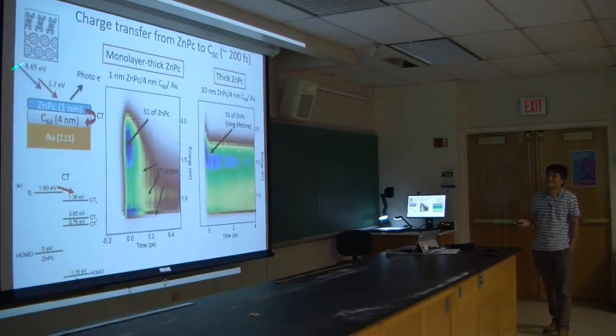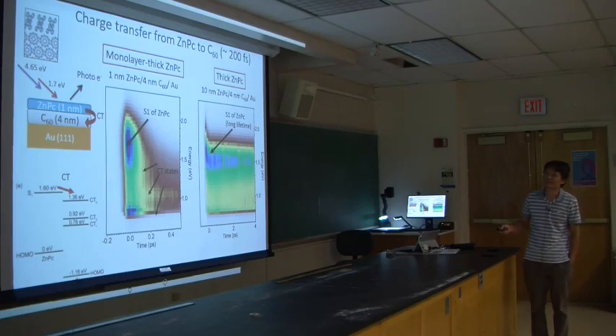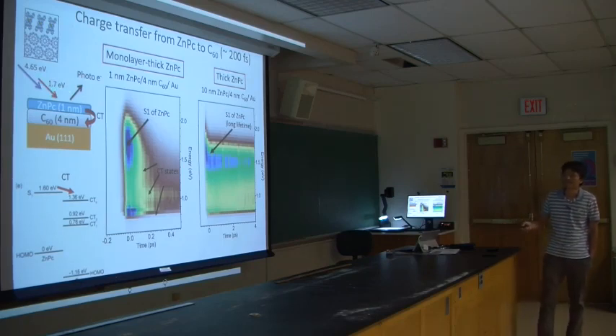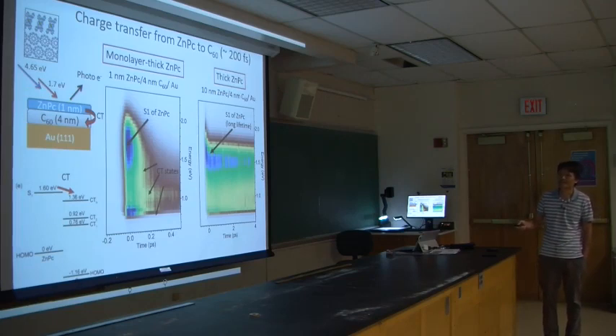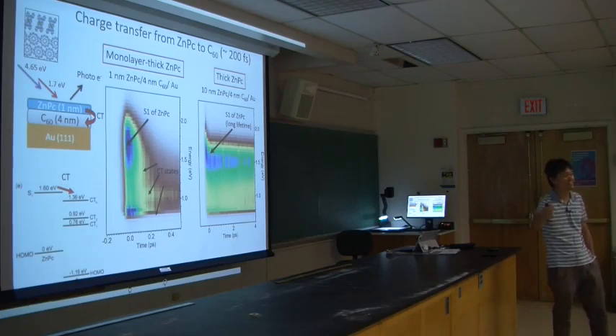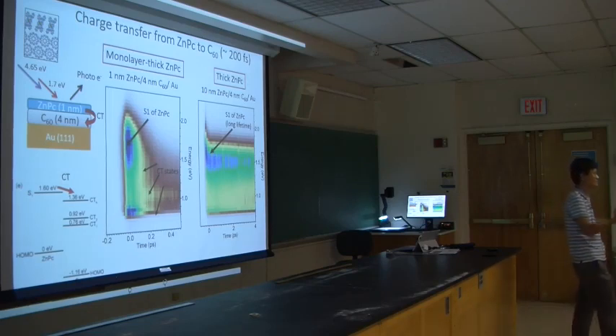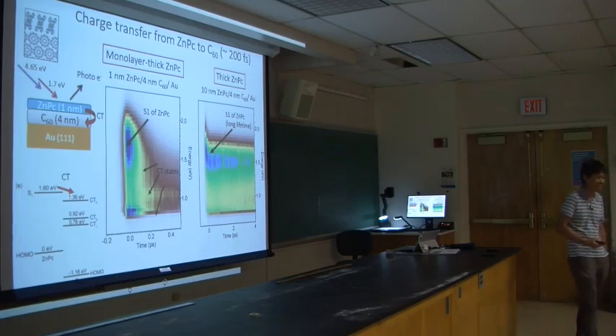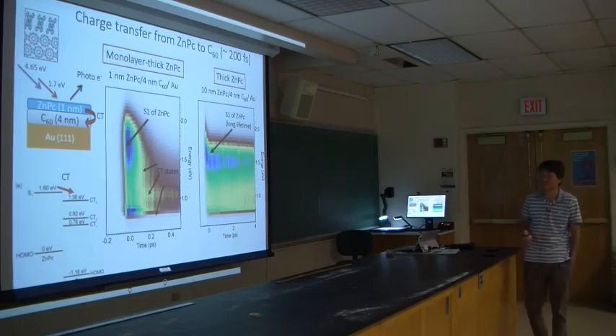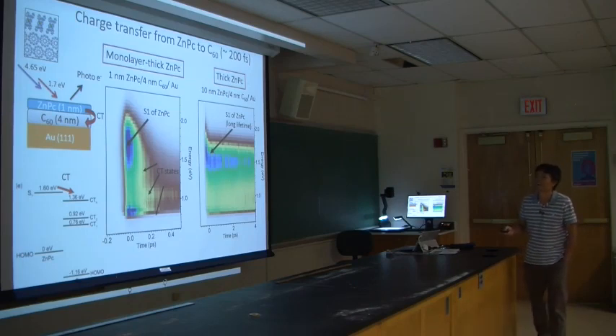Then we did this pump-probe experiment. We have a thin layer of donor here and then a thicker layer of acceptor here. We use a pump pulse of about 1.7 eV to pump the top donor layer. Once excited, an exciton is created in the donor layer, and then the electron transfers to the acceptor layer. Then we form these so-called CT excitons, and now we can study the properties of these CT excitons.